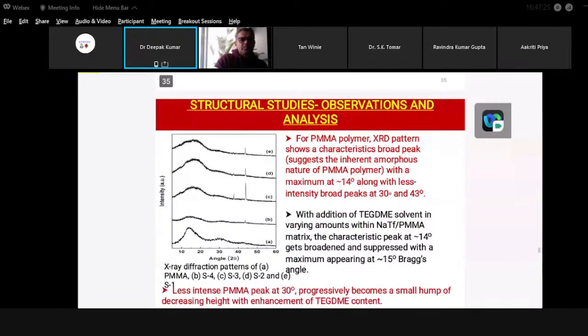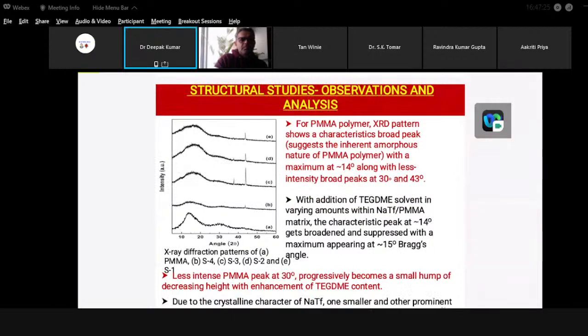For this electrolyte system, the XRD investigations are also performed. For this, the PMMA based electrolyte system can be seen to have peaks at 14 degrees, and in addition some humps are also there at 30 and 43 degrees. And once we incorporate the TEGDME solvent having different concentrations of the sodium salts, the peaks are reduced, which is indicating that the amorphous content is increasing. However, the feature of the NaTf salt content is not gone; it is visible and can be seen around 43 degrees.